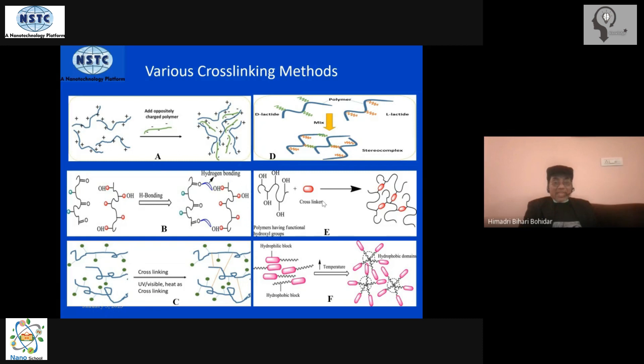You can see here, calcium has a valency of two—one side will bind to one pectin chain here, the other one will bind to another one, and so many of them will bind together and form a gel structure. By changing the concentration of the cross-linker, you can change all the properties of this gel. This is one example of it; there are many like this.